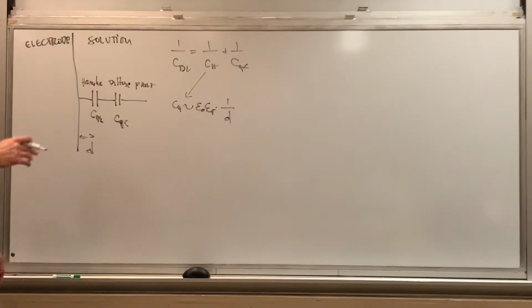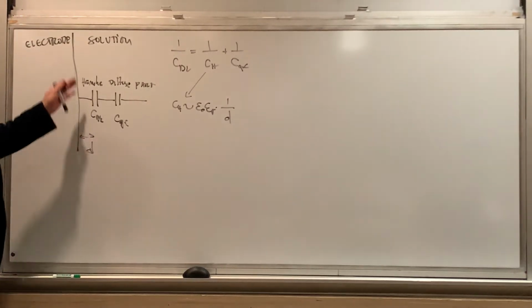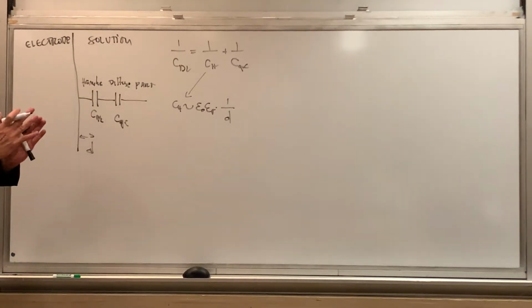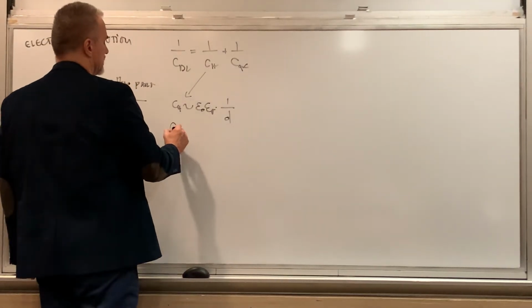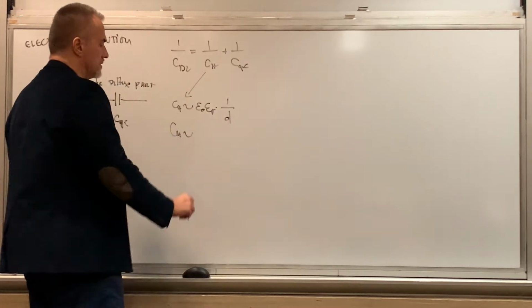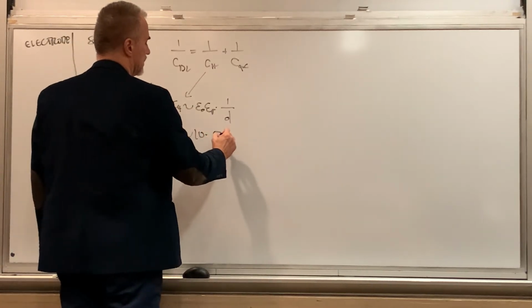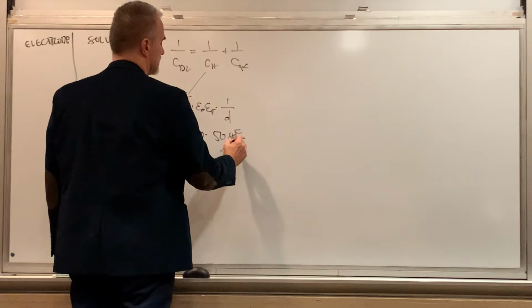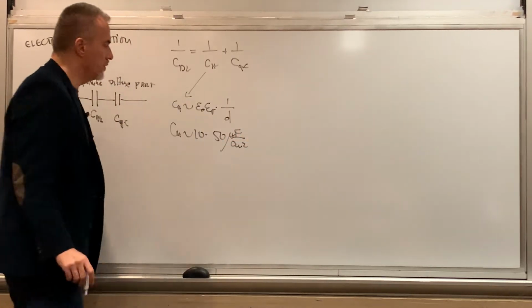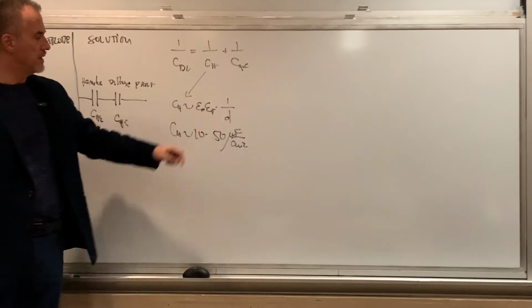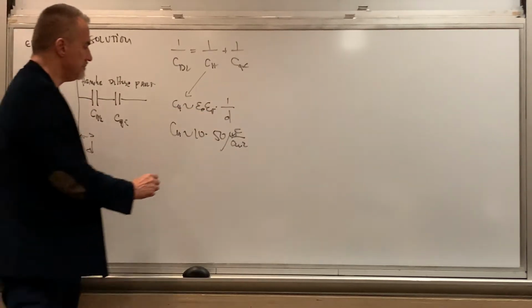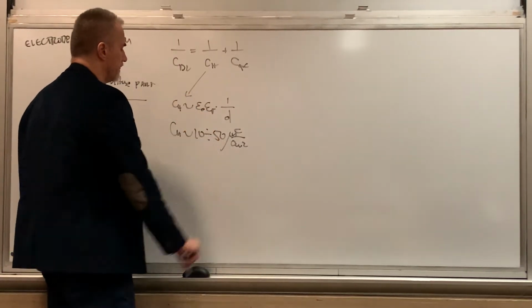I'm just going to round this up to the distance that we assume from the electrode's surface, for which you have basically this tightly packed layer. And we said that this is on the order of 10 to 50 microfarads per centimeter squared, depending on how we calculate the dielectric constant of water and what we take here for D, right?